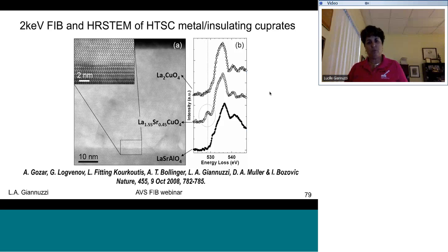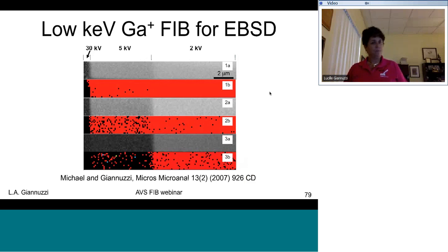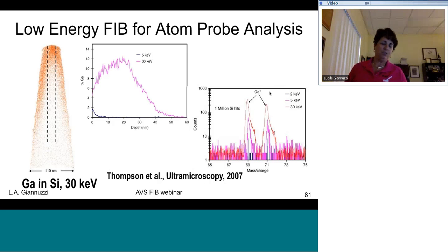This was working with Cornell, looking at STEM of high temperature superconductor metal insulating heterostructure layers. Very easy to see these different layers. This, of course, is very useful for doing EBSD analysis as well, which is also surface sensitive. So it improves the low energy signal, improves your hit rate of your EBSD analysis. And it turns out that 5 kV is absolutely necessary for atom probe analysis, and 2 kV is even better. So you can't do atom probe analysis with 30 kV, you just get too much implantation across the tip.